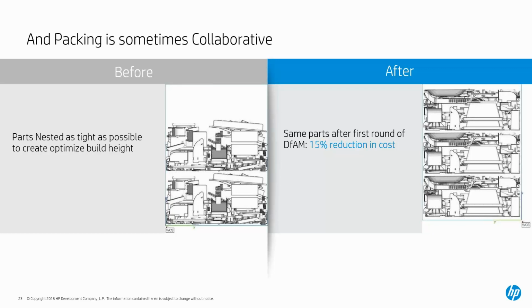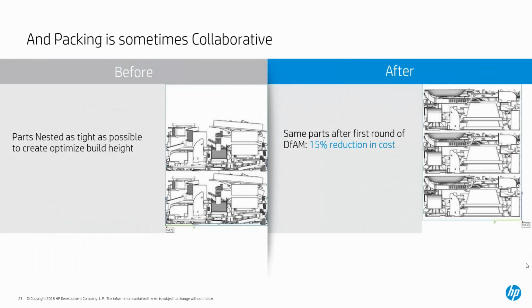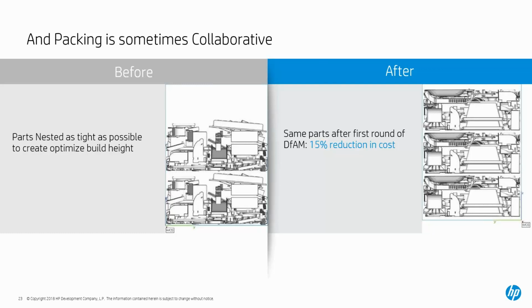The other thing that we started to do is look at how we fit the parts inside of a nest before DFAM. So when we took the traditional set before we did any DFAM and nested them in sets inside of the build chamber for the specific product, we found that we could only fit 2 full sets inside of it. But when we start looking at the folding strategy of unfolding that hinge part and doing the solo cupping and adding in the structural skeletal elements to the part, after we did all these different types of things and implemented them into the parts, we found that we could fit an entire another set into the build envelope of our 4200, and that gave us about a 15% cost reduction just by adding that into the build and applying different design guidelines to the parts in order to get the best performance.